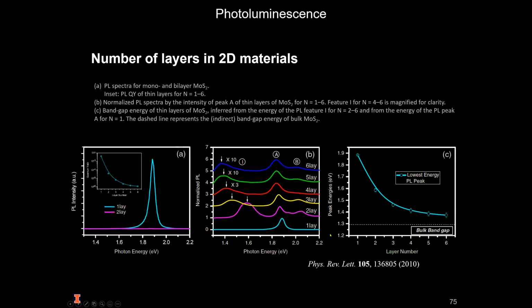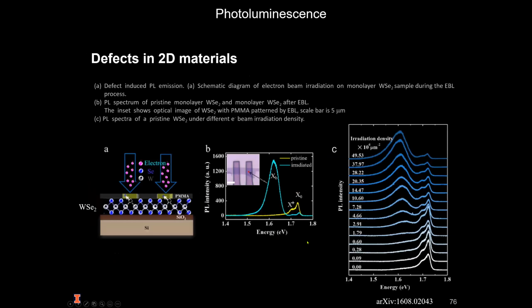Photoluminescence can be used to study defects in these materials as well, being a great complementary technique to Raman spectroscopy. Here is the evolution of the photoluminescence spectrum as a function of electron irradiation intensity for tungsten diselenide monolayer.